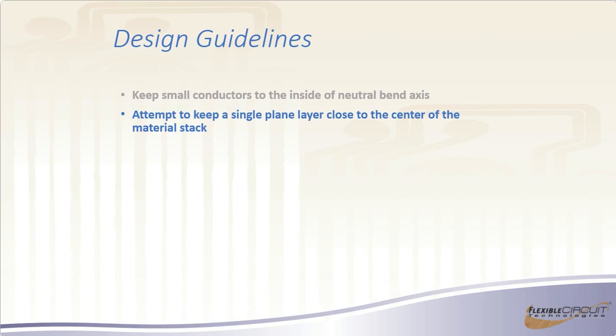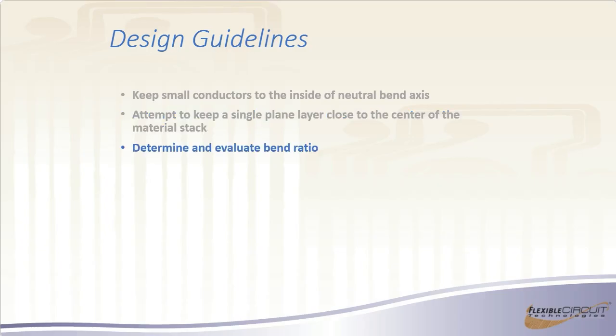If you have a single plane layer and you can keep that close to the center of your stack, as we talked about earlier, that will tend to draw that neutral bend axis into that area and keep your neutral bend axis hopefully reasonably centered so you can equalize the forces between the inner and outer layers. And determine and evaluate your bend ratio. Again, this is so important.